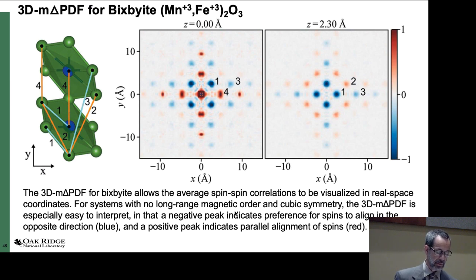So here is shown the 3D magnetic delta PDF for Bixbyite. It allows the average spin-spin correlations to be visualized in real space coordinates. For systems with no long-range magnetic order and cubic symmetry, this function is especially easy to interpret, in that the negative peak indicates a preference for spins to be aligned in opposite directions, shown here in blue, and ones that are parallel are indicated in red. And you can correspond these peaks with the separations of the nearest neighbor or next nearest neighbor and so forth atom pairs in the structure.